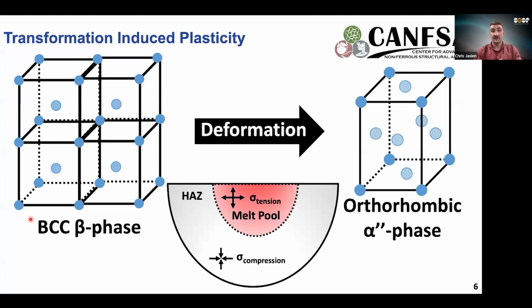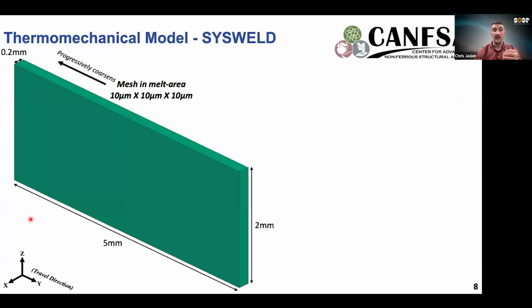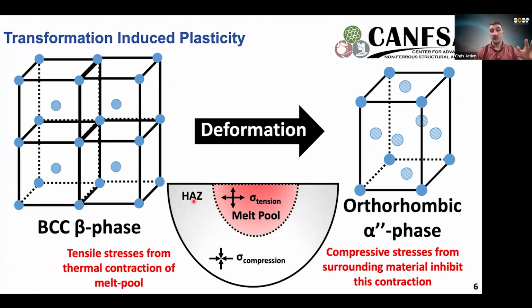And so just a schematic shown here is that these internal deformations arise from the solidification process, as well as some thermal contraction and things like that. So within the melt pool, we are solidifying and we're rapidly cooling. So we're getting some residual tensile strains in the melt pool, and these originate from the thermal contraction of the melt pool. And then in the region surrounding it, which I'll call the heat affected zone, or the HAZ, we see that it tries to inhibit this material from contracting. So we get a residual compressive strain. So it causes this behavior in the material.